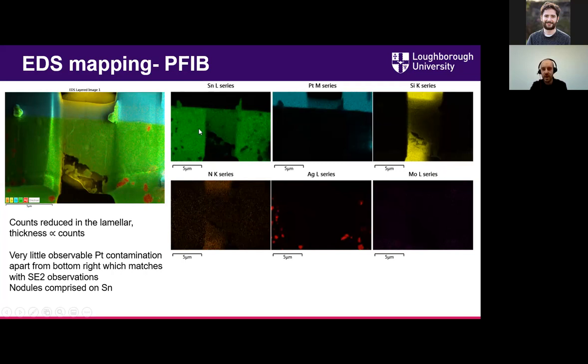It also shows that, as we have thicker sides, this is much better for EDS. It's far easier to pick out our silver precipitates. Whereas where we have the thin sample, we have lower counts, so it's more difficult to identify the elemental composition, although we get better spatial resolution.